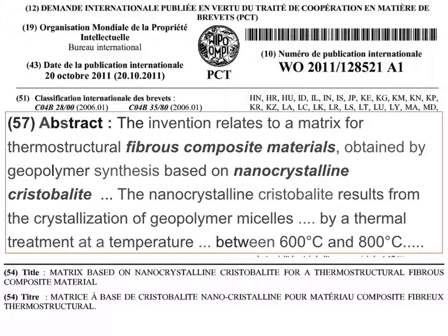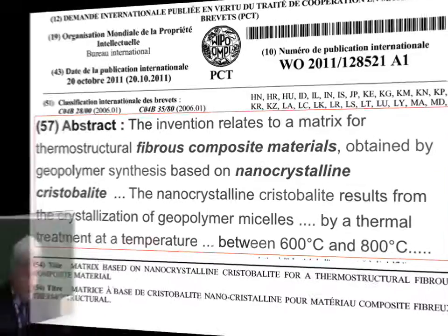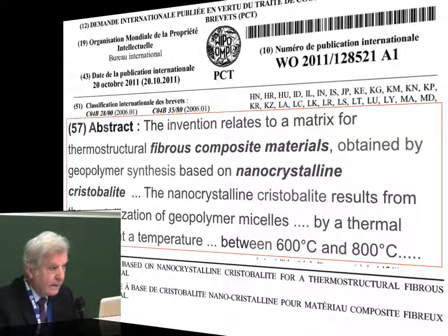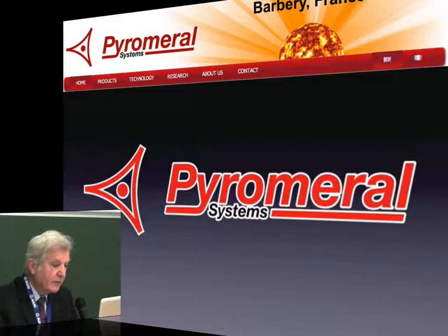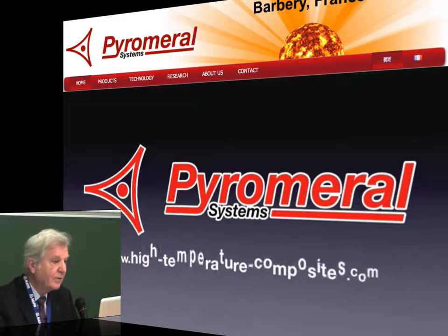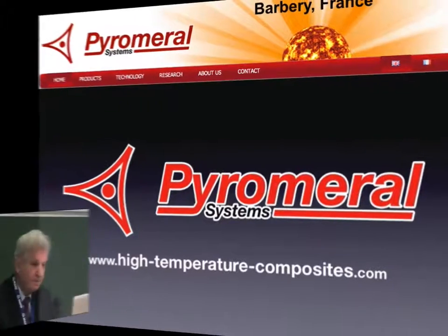The nanocrystalline cristobalite results from the crystallization of geopolymer micelles by a thermal treatment at a temperature between 600 and 800 degrees C. And I show you, when you go to the site, a wonderful video doing.